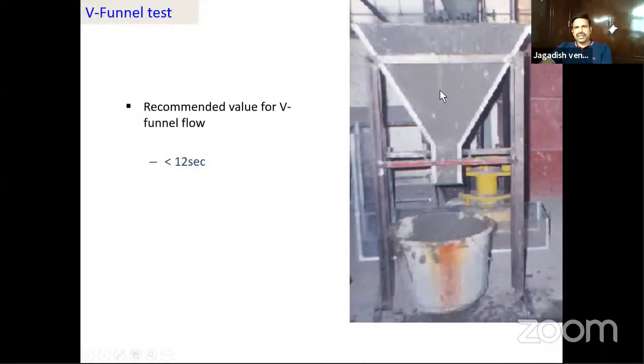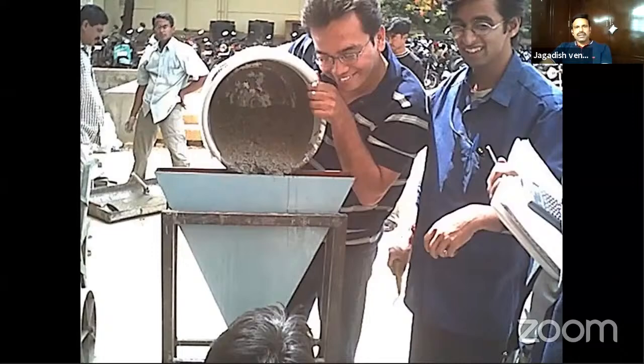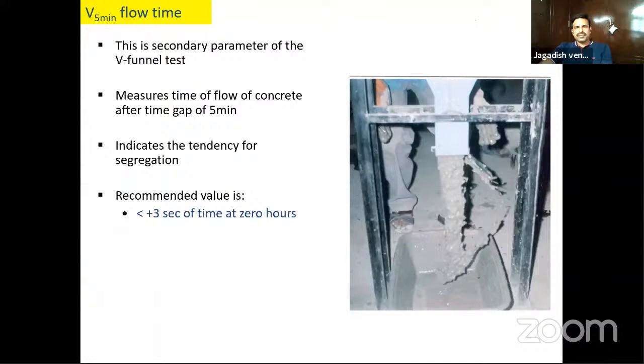So this was the initial V-funnel I made way back in 2002. This is this particular V-funnel. And there is one more measurement you do using the V-funnel, that is the V5 minutes flow time. How do you do it? You place the concrete in the V-funnel and wait for 5 minutes. After 5 minutes, you open the bottom door. What happens when you place the concrete and wait for 5 minutes? If the mix is not good, all the coarse aggregate gets collected or settled at the narrow end.